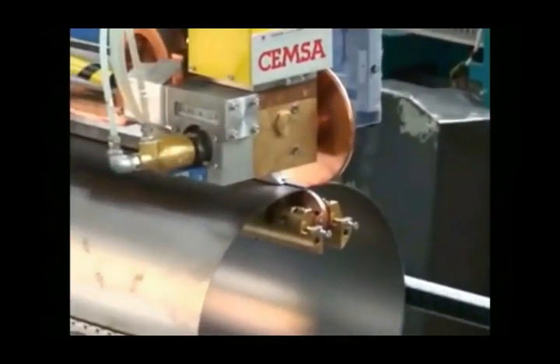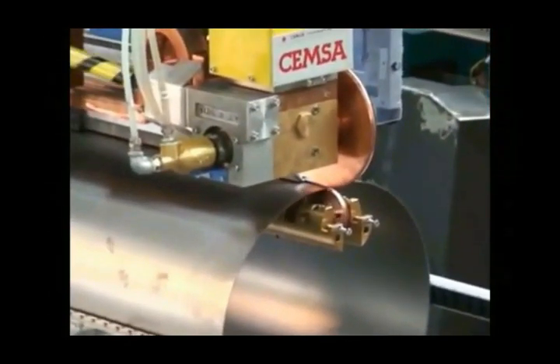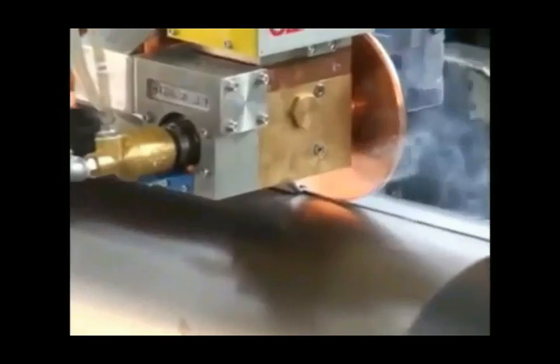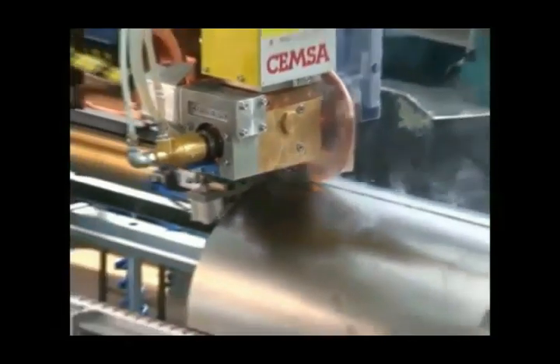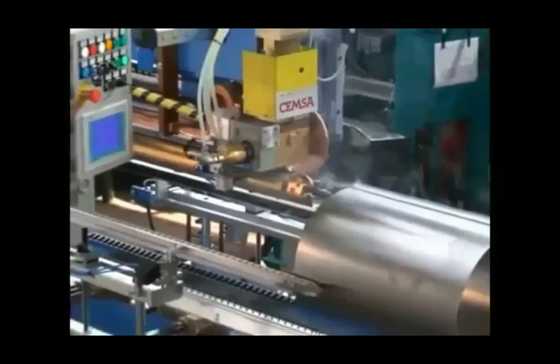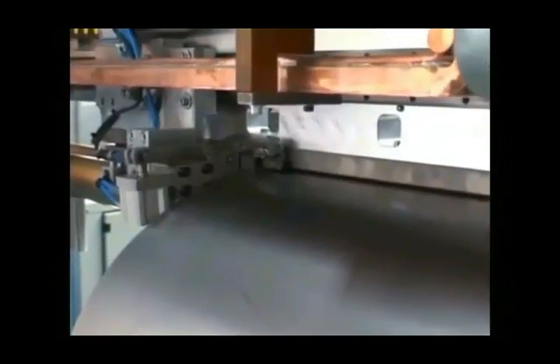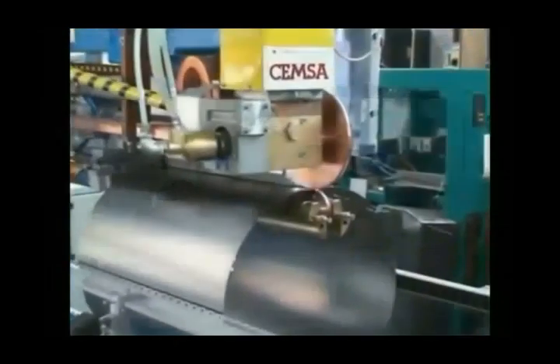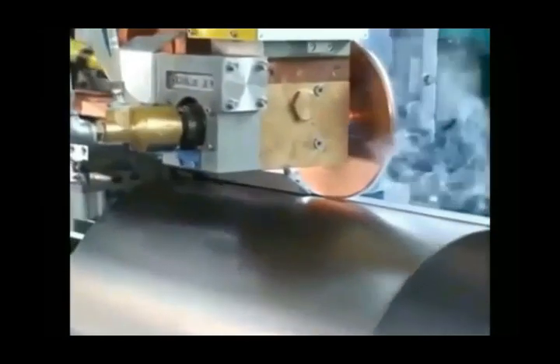This video shows seam welding the outer case of a water heater. The water heater case is also made out of zinc-coated steel. During welding, a large amount of smoke comes out of the faying surface. This is because the welding temperature exceeds 907 degrees Celsius.